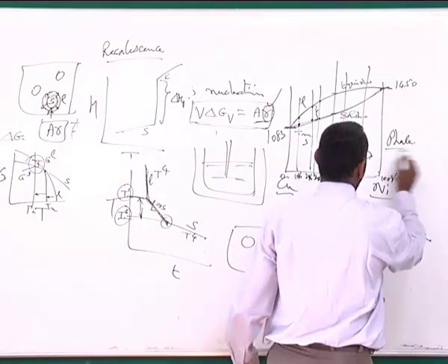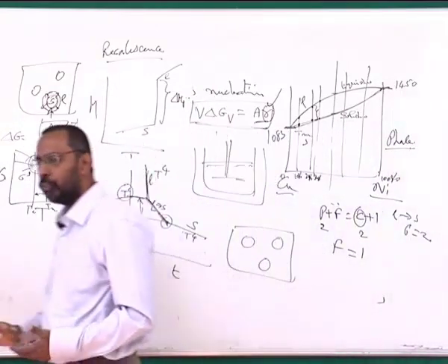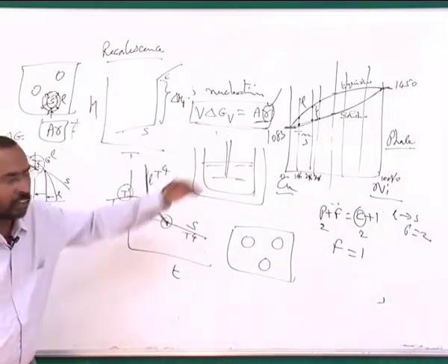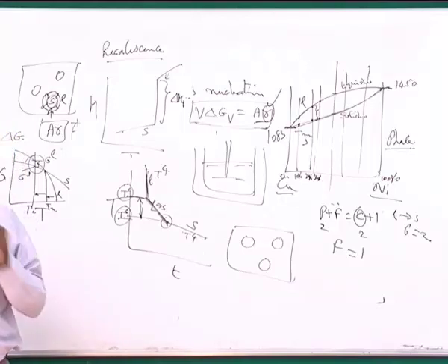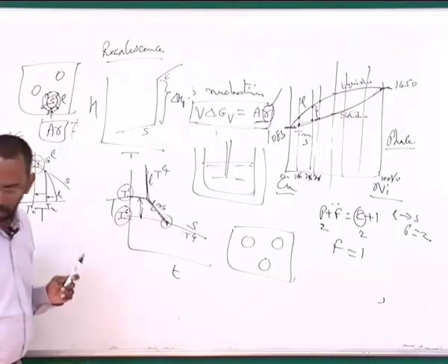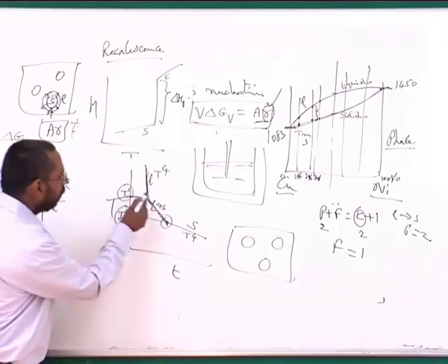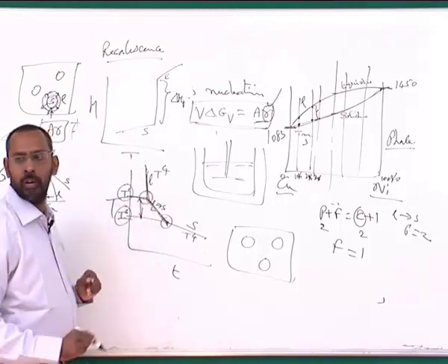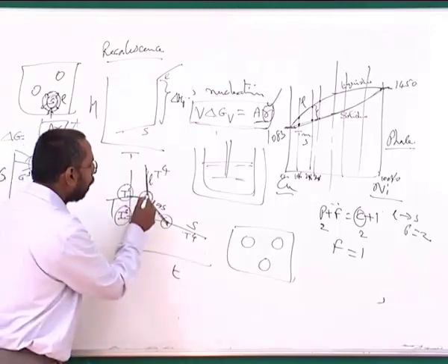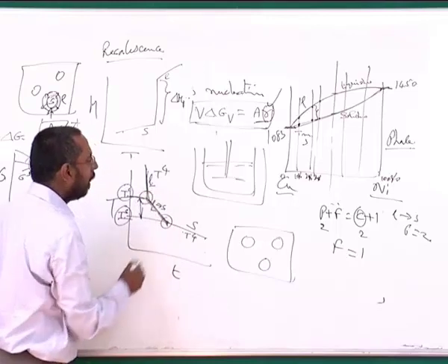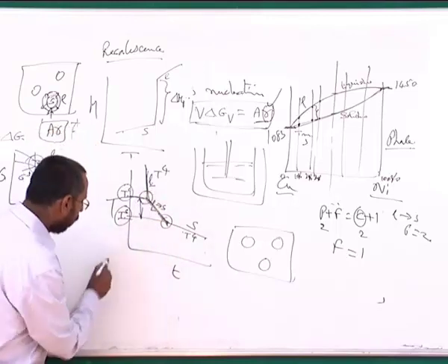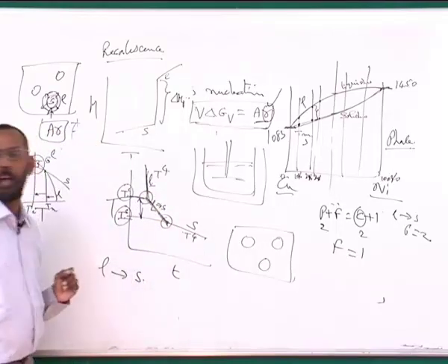thermal analysis. So thermal analysis is very useful to understand such phase diagrams, but there are limitations. What are the limitations? Because here, if you use a thermal analysis, the thermal analysis is able to give you this particular slope change only when there is a significant amount of enthalpy difference between the two phases that are involved. Liquid to solid, there is a significant enthalpy change.